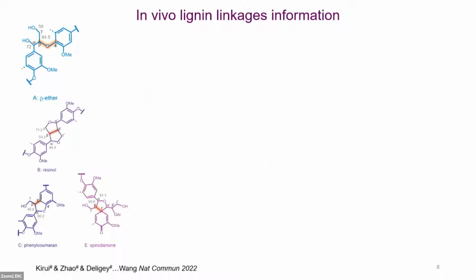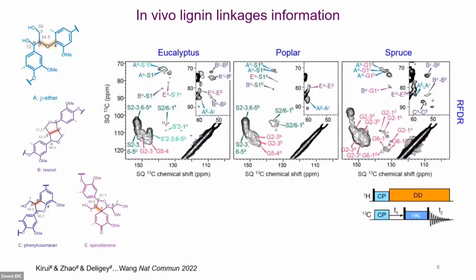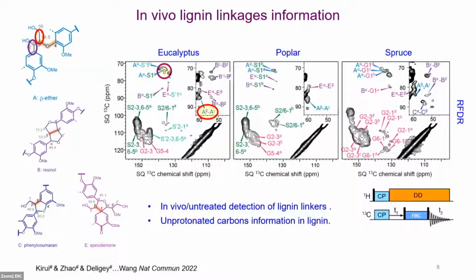The lignin aromatic rings are connected by different kinds of linkages, for example, beta-O-4 and beta-beta. Here, we use the RFDR experiment to successfully get the linkage information, such as this one, the S1 to A alpha on the left top side, and also the A beta to A gamma, and so on. So we can get this linkage information in untreated plant samples in the real in situ environment. Another important thing is we can get the unprotonated carbon information in the lignin. Why is it important? In current lignin research, solution NMR, especially the HSQC experiment, is a major method to detect lignin information, but it's hard to give us the unprotonated carbon information. Solid-state NMR can do it.